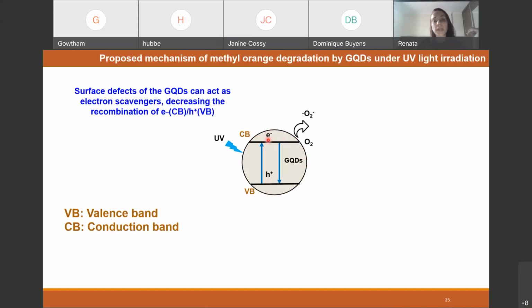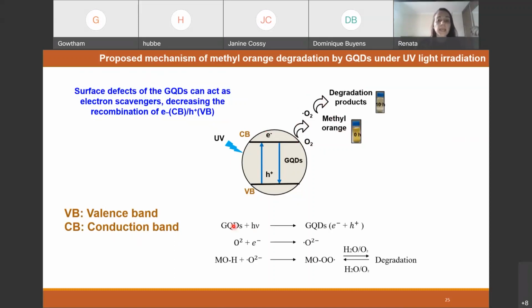The photogenerated electrons react with oxygen, producing superoxide radicals, and these radicals react with methyl orange, degrading it in solution. These are the equations that represent the mechanism. Graphene quantum dots are activated by UV-Vis light, producing electron-hole pairs. There is a mistake here, because this 2 should be subscripted. In the presence of electrons, oxygen produces superoxide radicals, and these superoxide radicals react with methyl orange, degrading this